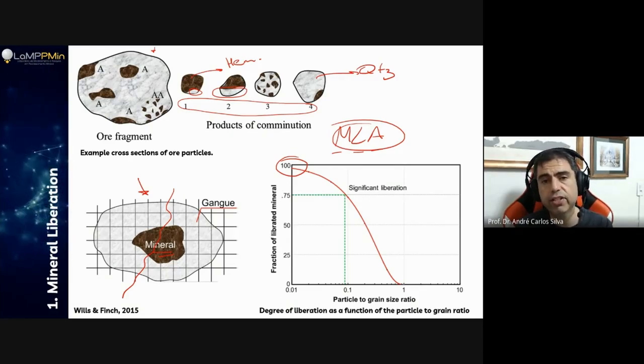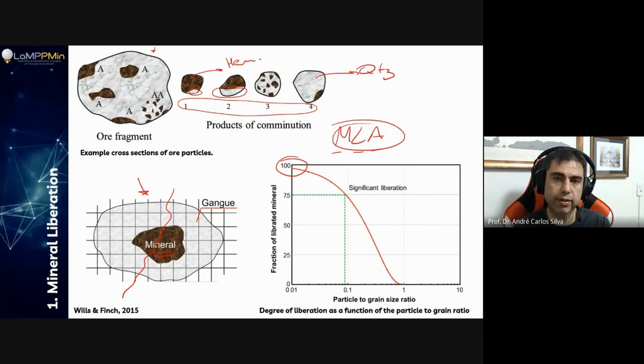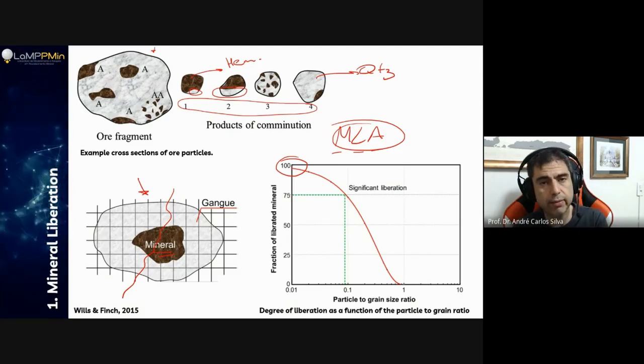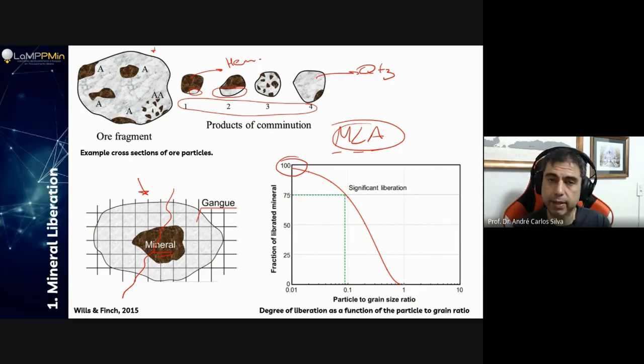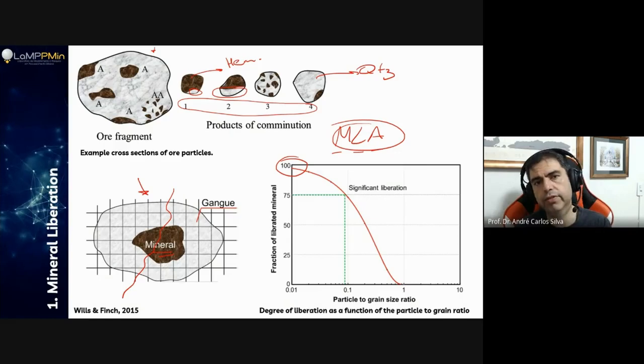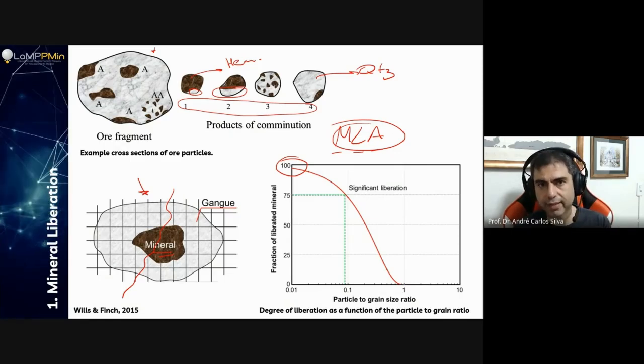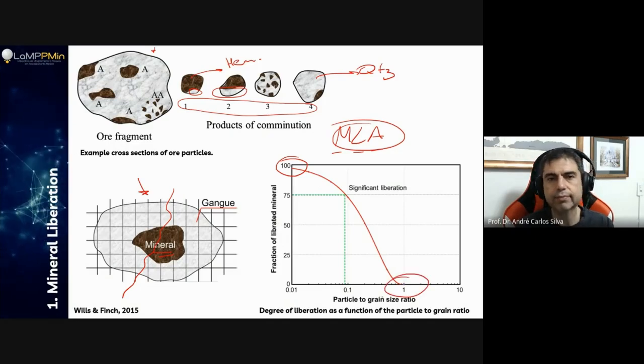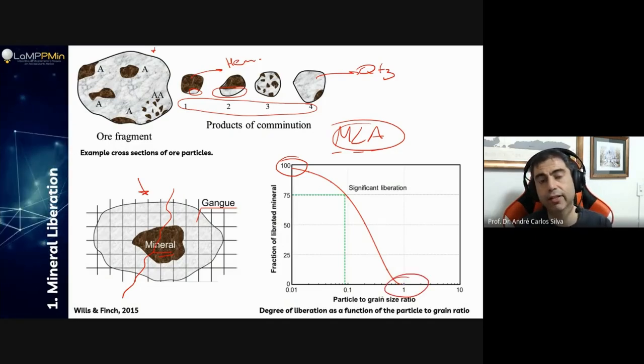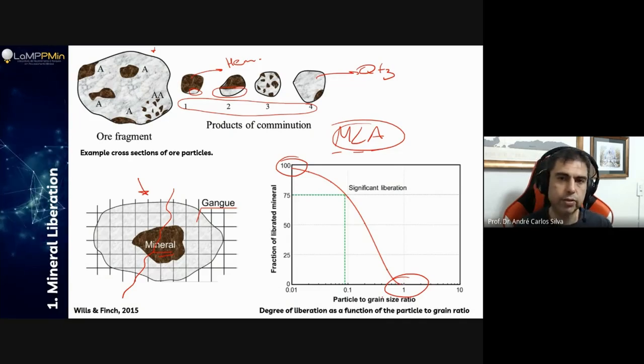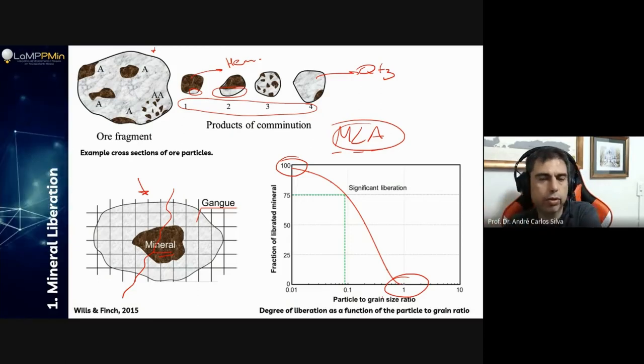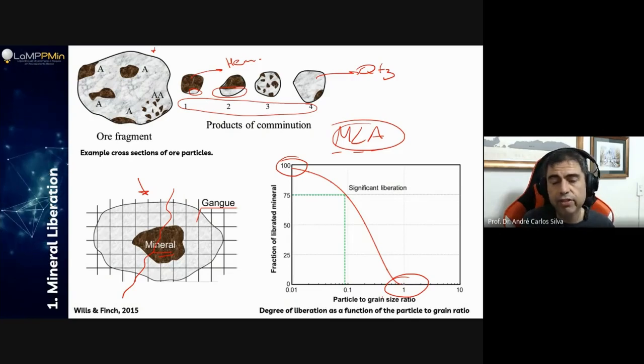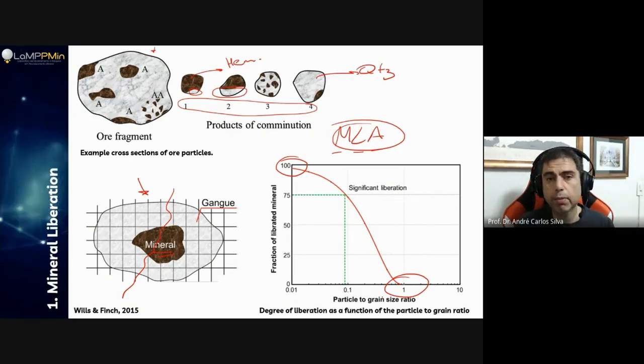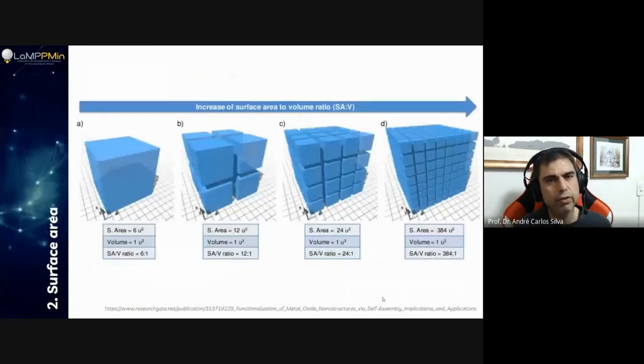So what is the definition of liberation? It's the amount of material in one specific particle size, okay, that we have the number of liberated particles, or 100% particles that I want to concentrate, divided by the amount of particles that I have in that fraction. So in this case, I don't have a single particle that is not associated with gangue minerals. Okay. So again, this is quite easy to understand. So if I go to a coarse fraction, then I'm gonna have almost 0% or even 0% of mineral liberation, and if I keep grinding, milling our material, we're gonna eventually reach a very high level of liberation, probably something near 100%. Definitely not 100%, but near it.